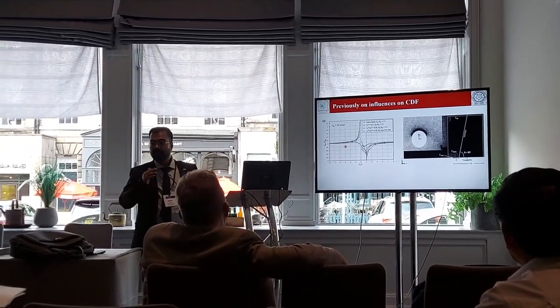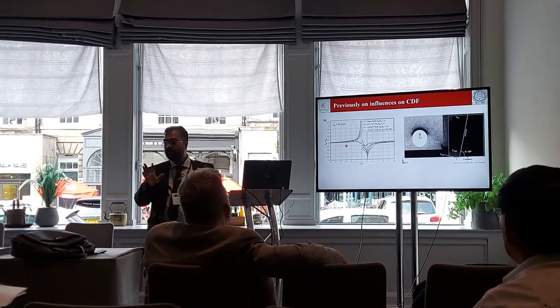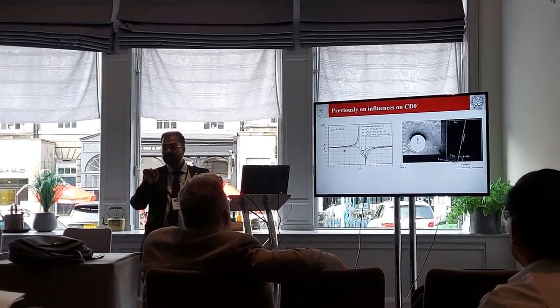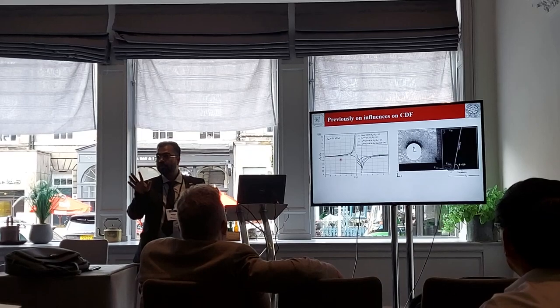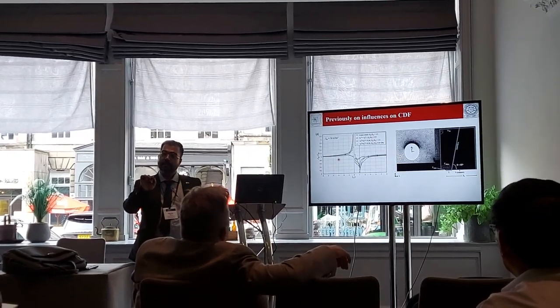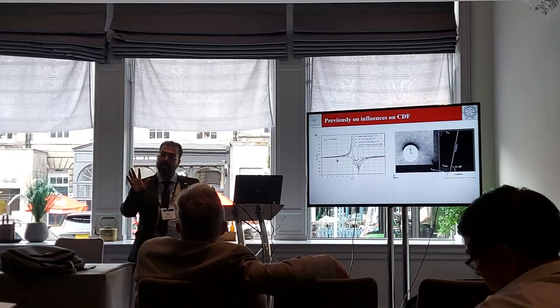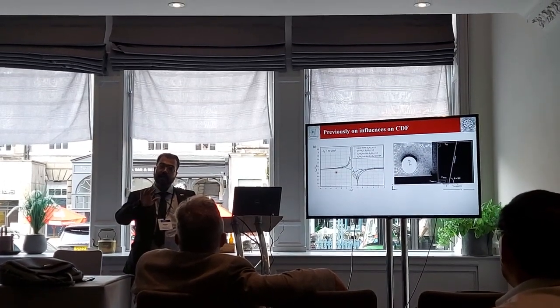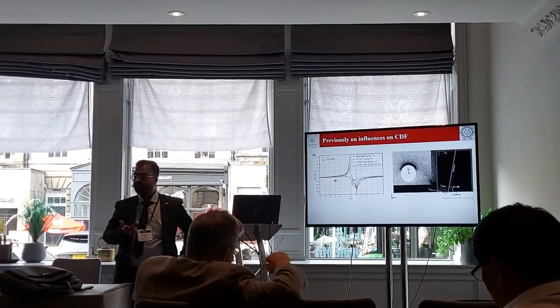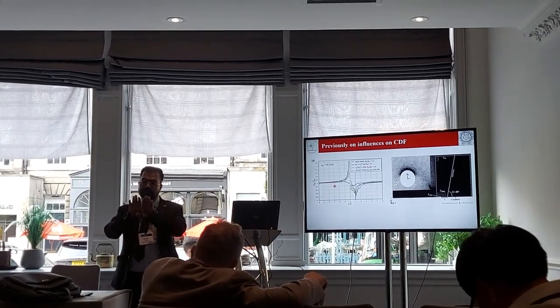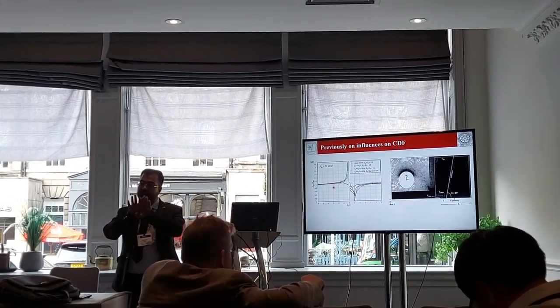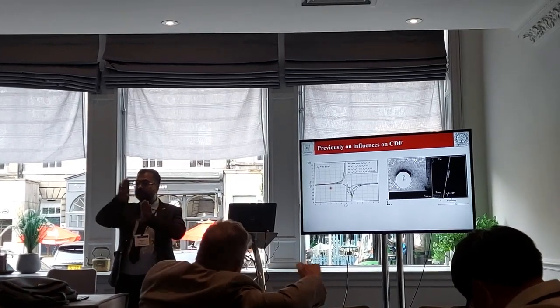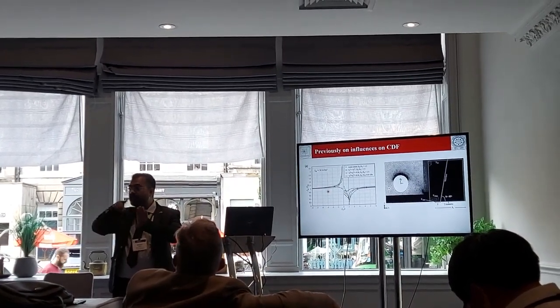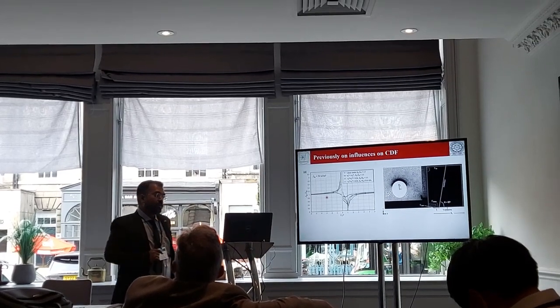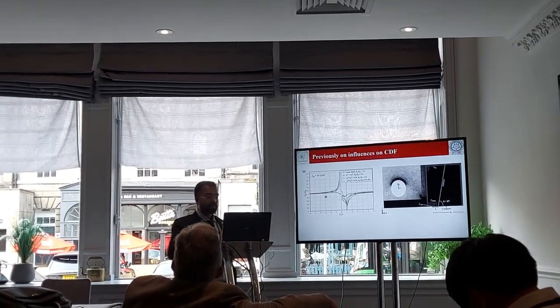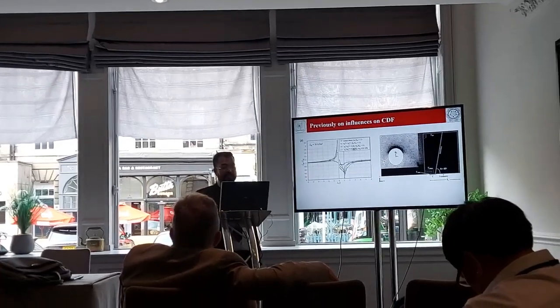What is happening at the first interface, if the weld zone is overmatching, is that the crack is transitioning from a normal yield strength to an overmatching material. So you can say that it is transitioning from a compliant material to a stiffer material. At the second interface, the reverse phenomenon is happening. If you have only two materials and one interface, then that effect will be different. If you have an interlayer, so you have another material behind it, then you will have a reverse phenomenon happening. In this case, the effect has been calculated using configurational forces.